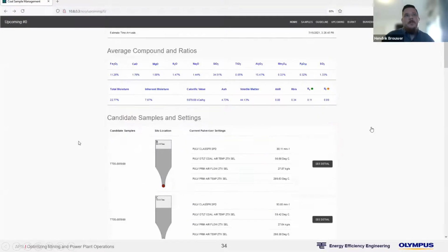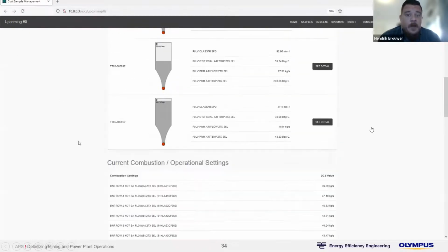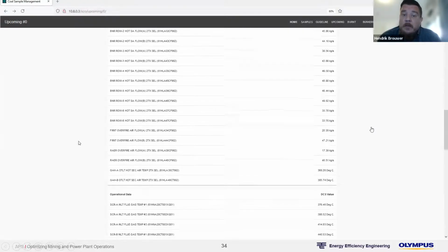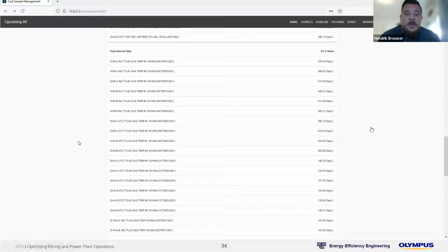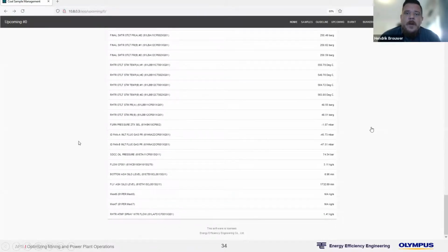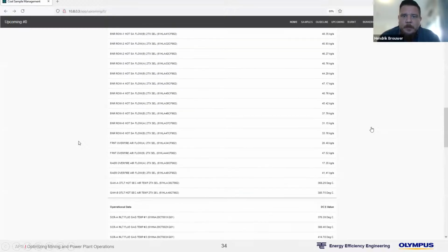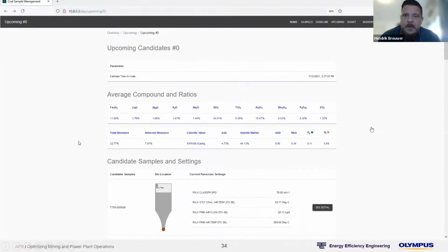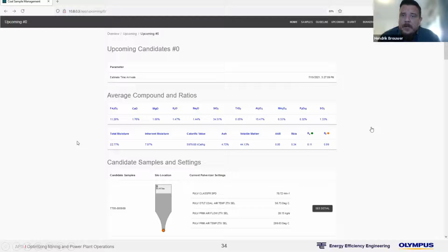So this is ample time for us to adjust mill speeds, primary air, velocity and volume, secondary air, velocity and volume, all in consideration with the furnace exit temperature and the current ash fusion temperature. Now, certain elements might fuse at 1100 degrees. Certain elements might fuse at 1200 or 1300 degrees. So this really gives us the opportunity to maximize our thermal conductivity and thermal efficiency, and therefore improve our boiler efficiency by keeping this ash in a solid state, easily removed by the soot blowers, and therefore not building up on your tubes, keeping your economizer exit temperature at optimal levels.